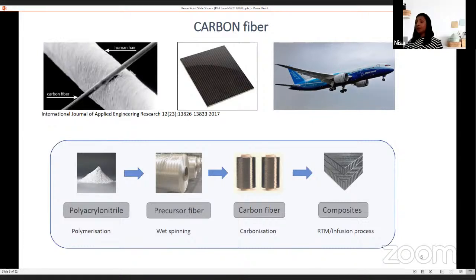This PAN undergoes a process called wet spinning. Here we are extruding the polymer into a solvent, which is called a coagulation process, and that's the way it forms a white fiber or precursor fibers. These precursor fibers, when they experience high temperature treatment over 1000 degrees, form carbon fibers. These carbon fibers are later embedded in a polymer matrix to make structural composites.